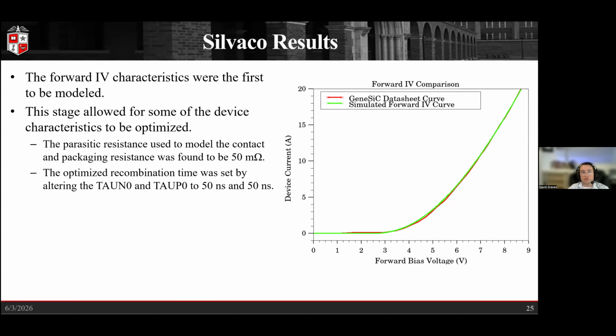And so with that, we began to model the characteristics of the device, beginning with forward IV. With this, the two big parameters that we were able to extract in our TCAD model were the packaging and contact resistance, which we found to be about 50 milliohms, and then the recombination times for the device. By altering the recombination times, we're able to adjust the knee portion of our forward IV curve. In order to get it to match relatively well to our datasheet curves, we found that using a tau n naught and a tau p naught of 50 nanoseconds was ideal.